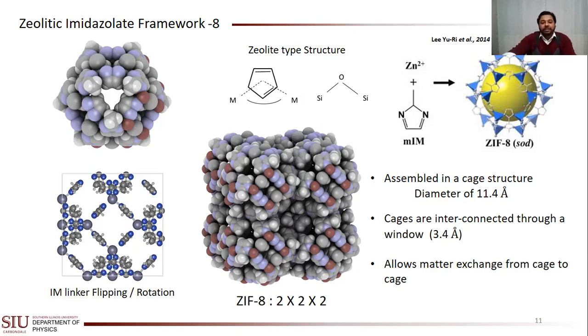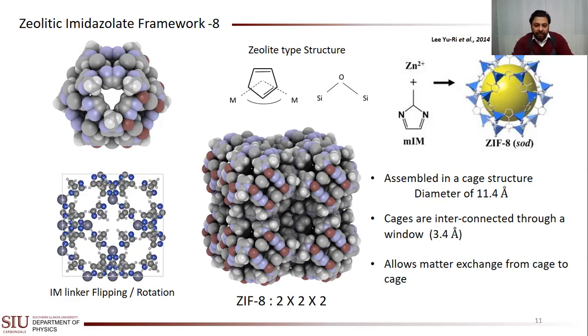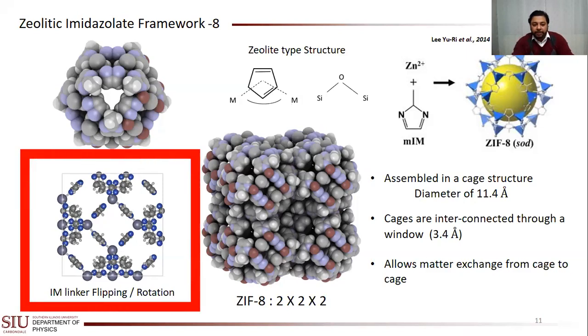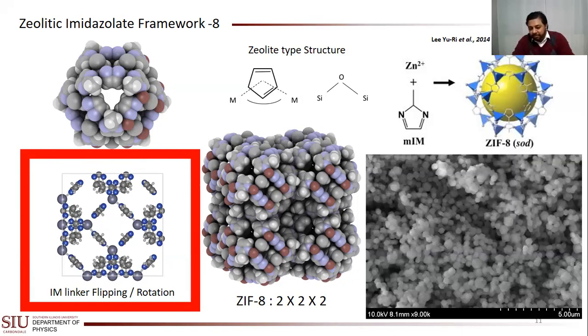So that's the uniqueness of this ZIF-8, and that has been investigated for a couple of years now. There have been so many definitions of this rotation effect, and I will talk about that a little bit later. I also want to show you a real-time picture, an SEM image of this ZIF-8. It's a crystalline structure, so you can see that under the microscope. It's a really crystalline structure, almost close to the zeolite structure.